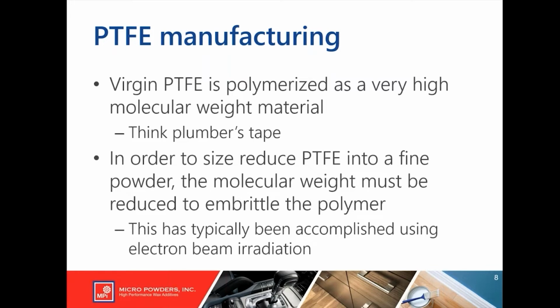So let's talk about how PTFE is manufactured. If you have virgin PTFE, this is polymerized and it's a very high molecular weight material. If anybody out there has ever done any plumbing work and you know what plumber's tape is like, it's very stretchy, it's not brittle at all. This is basically virgin PTFE, very stretchy, rubbery material. And you're never going to be able to take that and convert it into a very fine powder. So in order to take that virgin PTFE and reduce it in size to a small particle, you have to basically break down the molecular weight of that virgin PTFE to embrittle the polymer. Typically, you'll take the molecular weight down to, say, 25 to 50,000 molecular weight. And typically, for most suppliers, this has been done by using electron beam irradiation. You take the virgin PTFE and run it through a process where you irradiate it, and basically you're chopping those high molecular weight chains down into lower molecular weight fragments, if you will.